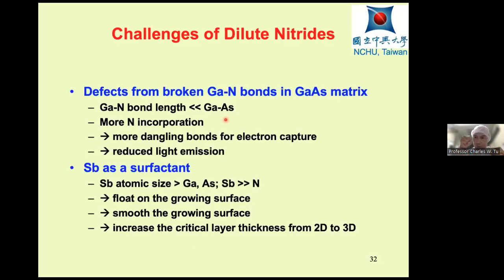We want to put nitrogen into the arsenic sublattice, but the gallium nitride bond is much shorter, as you saw in the gallium nitride lattice constant, much shorter than gallium arsenide. And so when we put a lot of nitrogen in, you get broken bonds, because the strain is too large. And once you have broken bonds, these are dangling bonds, and they can capture electrons, and so they reduce the light emission.